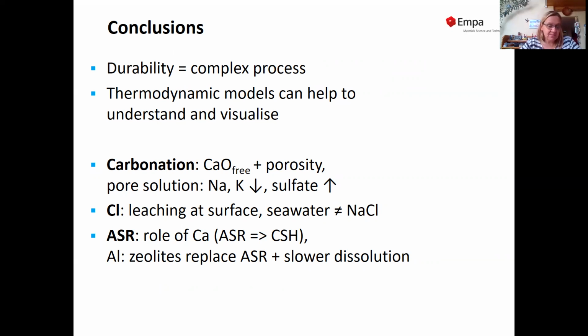ASR, the availability of calcium plays an important role, and also the availability of aluminium plays an important role, as this can prevent the formation of ASR products while some N-A-S-H or zeolitic precursors are formed.